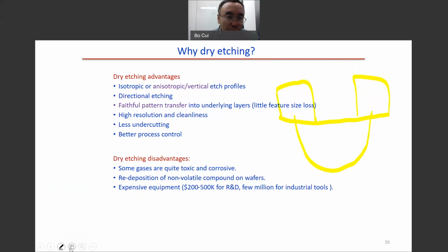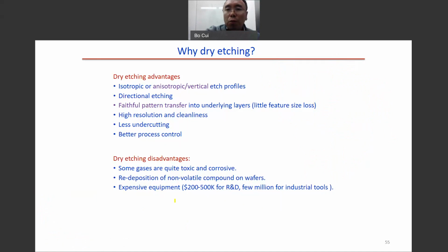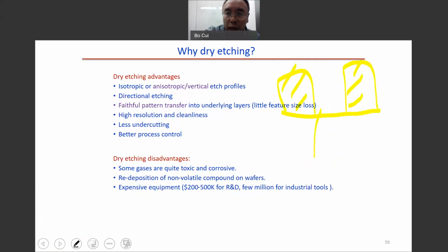What we want very often for microfabrication is the vertical profile. That means if you have here the etching mask, after etching we want the etch profile to be something like this. It's a vertical profile. When we have the vertical profile, we can have faithful pattern transfer into the underlying layer. This means the feature size on the opening on the top is the same as the feature size on the bottom. This way we can maintain the feature size.